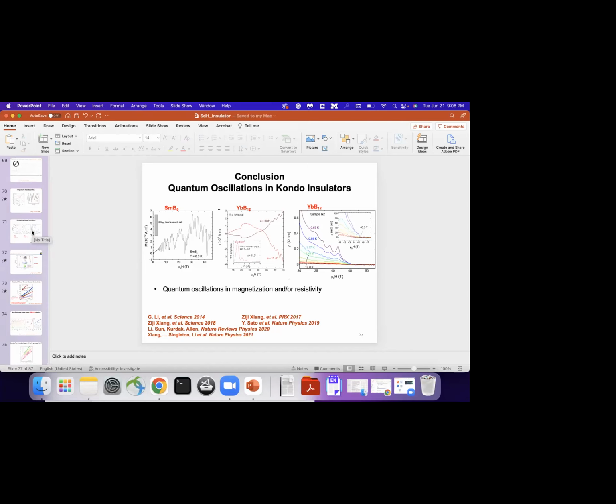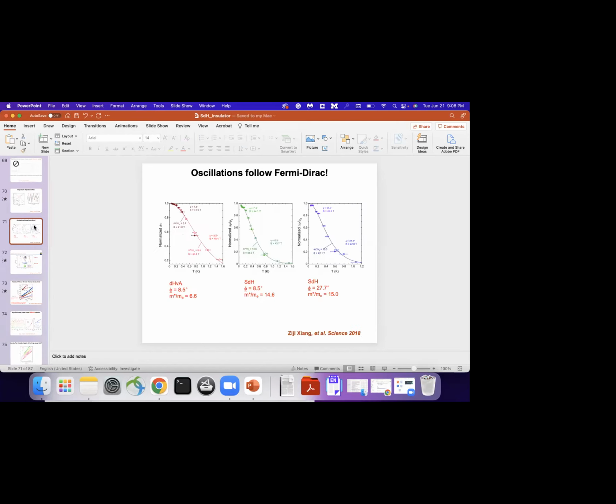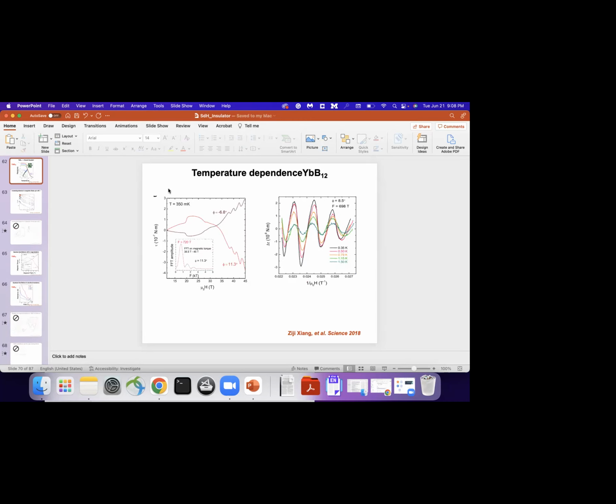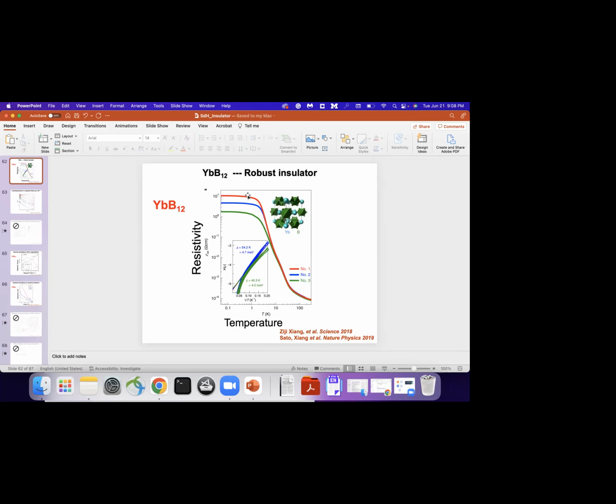That's a good question. My answer would be, not exactly, in the following sense. Maybe it's easy to look at the temperature dependence. My resolution tells us eventually about 1.1 or 1.5 Kelvin-ish for both samples. I'm not able to resolve much oscillations, right? So back to the transport phenomena, it's roughly around here. But you see that this is not an exact plateau like a quantum Hall plateau is, right? Because in this logarithmic plot, it's still increasing slowly, which means it's a much weaker divergence of resistivity, but it's not exactly flat.